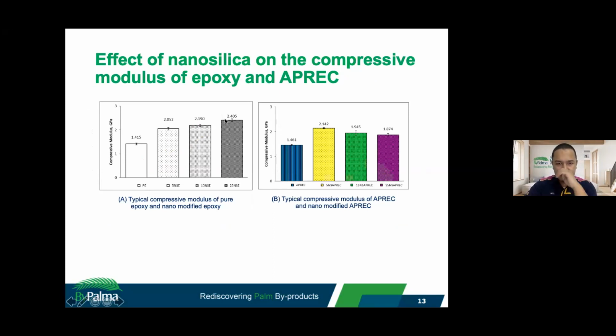Next, the effect of nanosilica on the compressive modulus of epoxy and APREC. As can be seen, this is for epoxy, and then this is for APREC. The compressive modulus of the nano-modified specimens is greater than the pure epoxy. And then for APREC, the compressive modulus of the specimens with nanosilica was higher than the pure APREC, but we have the highest in 5% weight of nanosilica, but it dropped when we added more weight percent of nanosilica.